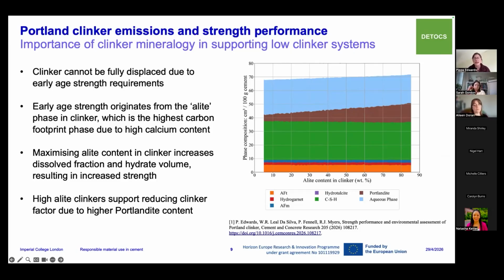So what we did was we studied clinkers, varying the concentration of alite in our model, compared to the less reactive but lower emission belite clinkers. And our modeling shows that by increasing the alite content, it increases the volume of hydration products at early ages, as well as the mortar strength, and results in more formation of portlandite, which supports the reaction with clinker substitutes. So optimizing the clinker composition can actually enable further substitution of clinker than we see in conventional cement mixes now.